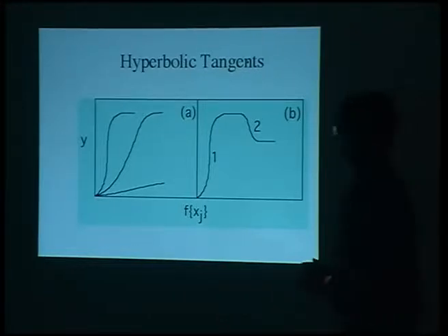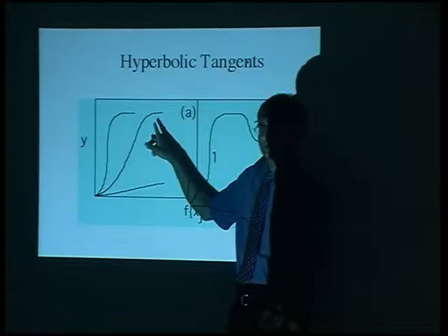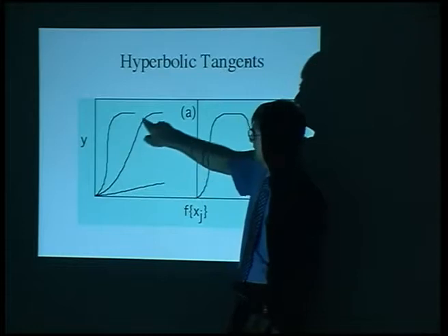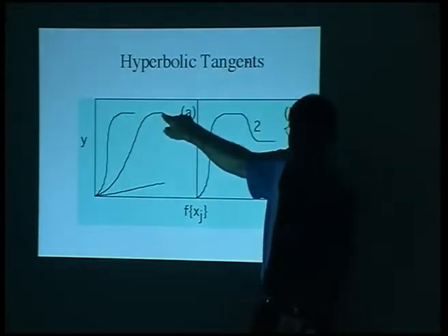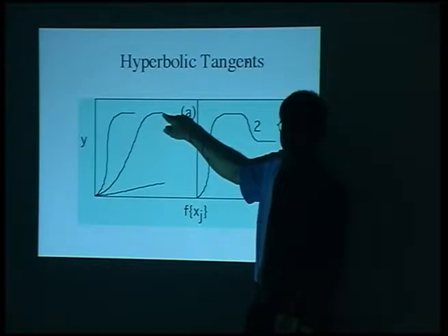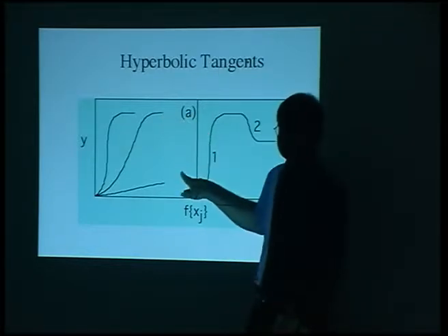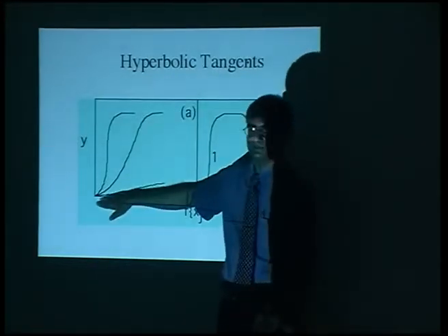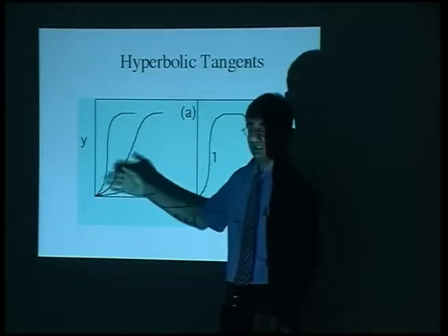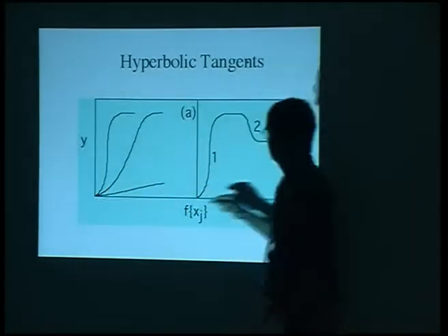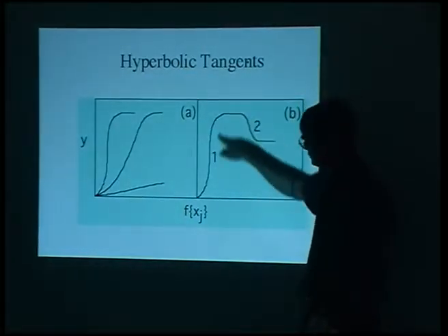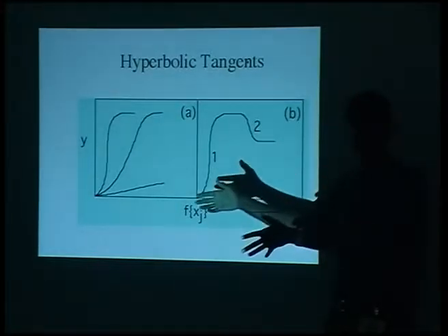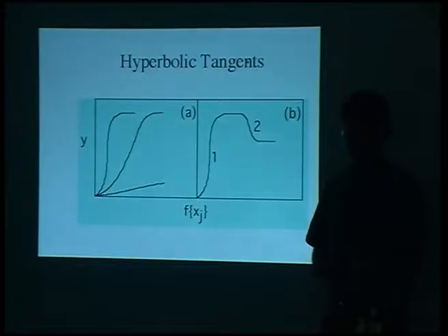We still have a problem, is that this may not be sufficiently non-linear. So for example, if I'm modeling the yield strength as a function of carbon, yes, it will increase, and it might even flatten out because it comes out of solid solution. But at some point we are going to precipitate graphite and the relationship might change completely. Okay? So this function, once I've defined it, is the same everywhere. What I need is for this to be even more non-linear. So why don't I add another hyperbolic tangent, and then I've got a function which is even more non-linear. I can carry that on, keep on adding these hyperbolic tangents until I get a sufficiently complicated function.